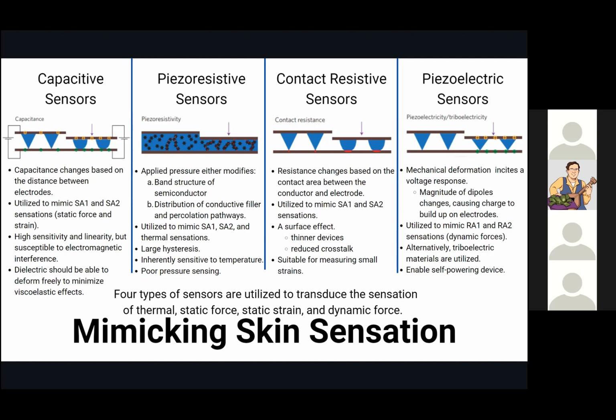And then finally, there's piezoelectric or triboelectric sensors, which are employed to mimic dynamic sensations. So the application of mechanical force to these materials results in the production of energy or voltage due to a change in the intrinsic orientation and therefore magnitude of the dipoles within the active layer. This in turn creates a small voltage. So the generation of energy upon mechanical deformation gives them the advantage of self-power. And it has been shown that vertical pillars of these materials can allow for arrays of much higher density and therefore sensitivity than human skin.